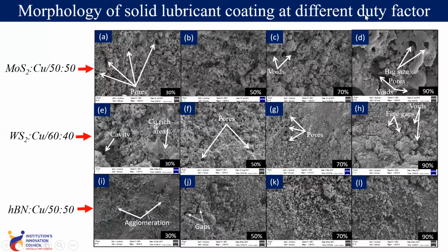Morphology of the solid lubricant coating at different duty factor. Basically, duty factor determines the efficiency of coating. So we observe that when we are increasing the duty factor up to 50% for MoS2 copper coating, a good surface is obtained. Although when we increase the duty factor to 90%, only arcing is obtained, because duty factor is the pulse on time to the total cycle time. Pulse on time divided by total cycle time.